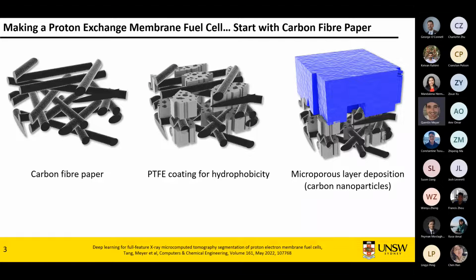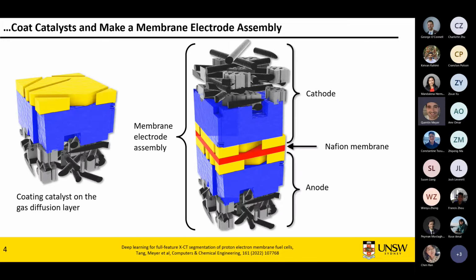So how do you actually start to make it? First step is you start with some carbon fiber papers. That's basically cellulose material that is typically pyrolyzed. Then from there, you coat them with PTFE for hydrophobicity. On top of that, you add a microporous layer or MPL, which is carbon nanoparticles mixed with PTFE. That gives you a GDL, which you typically use for all sorts of applications. On top of that, you typically coat your catalyst on the GDL or on the membrane. Then you press the whole thing together. You make the same on the other side, and that gives you your membrane electrode assembly, which is the building block for fuel cells.